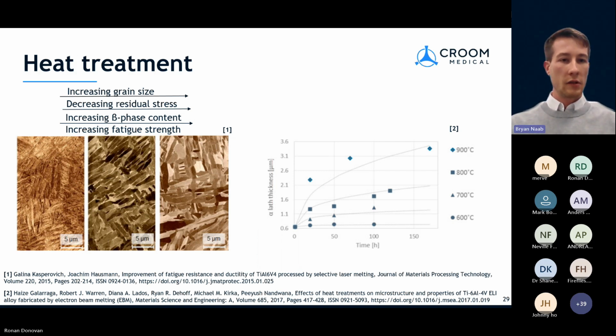The next thing that we can do is a standard heat treatment. I'm generalizing a little bit here. It is a bit more nuanced than this, but what we can say is that applying a heat treatment will increase the grain size, decrease residual stresses, and increase beta phase in titanium 6-4. And it will generally lead to an increase in the fatigue strength as well. What's great is there have been a lot of studies done to tell us exactly what heat treatments we need to apply to achieve a certain grain size. So a lot of the base work has already been done and has been published in literature.